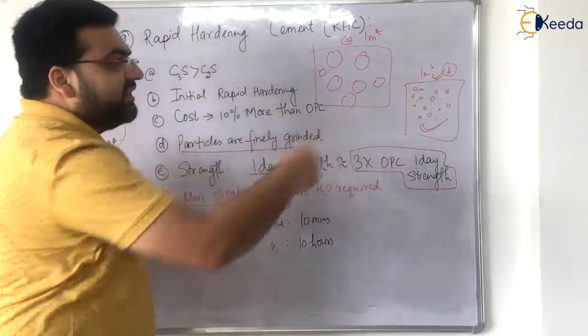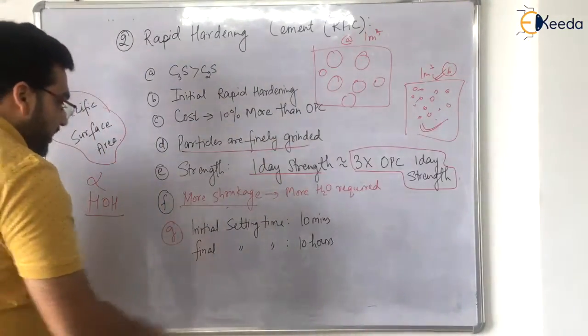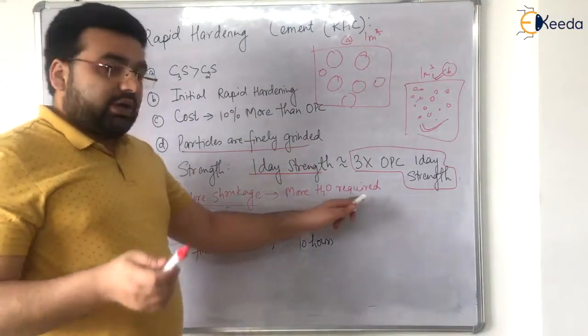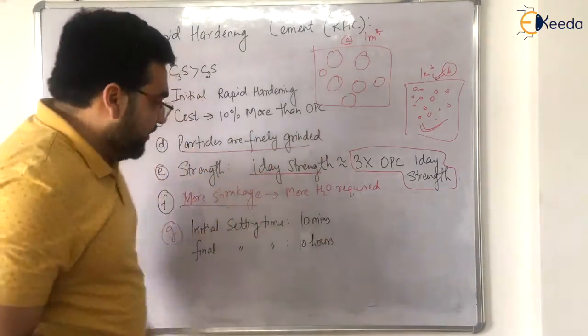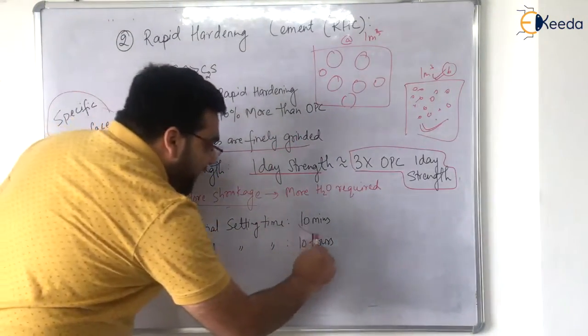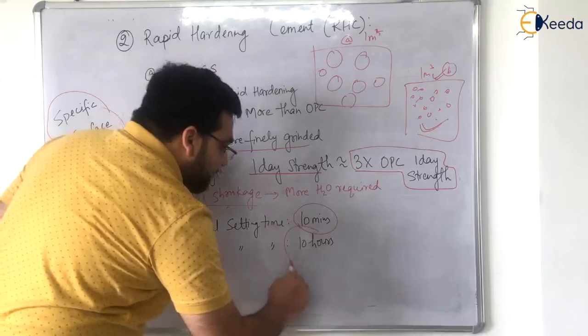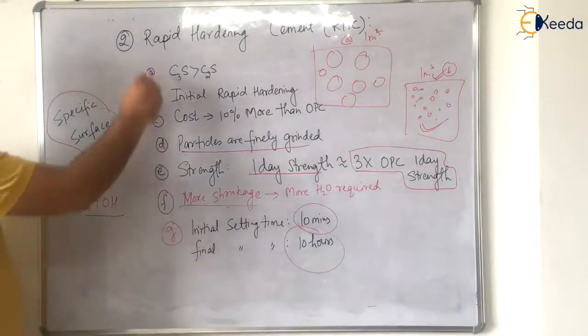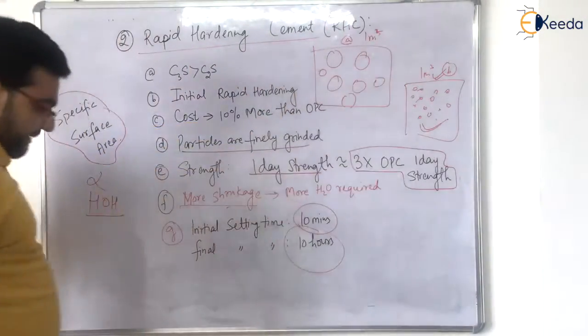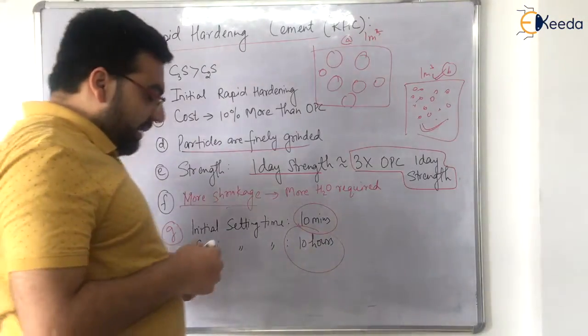Why? Because particles are finely ground. More shrinkage. Okay. If more shrinkage is there, more water will be required. I will explain that later in concrete. Now, initial setting time is 10 minutes and final setting time is 10 hours for rapid hardening cement. Okay. So that was all about rapid hardening cement.